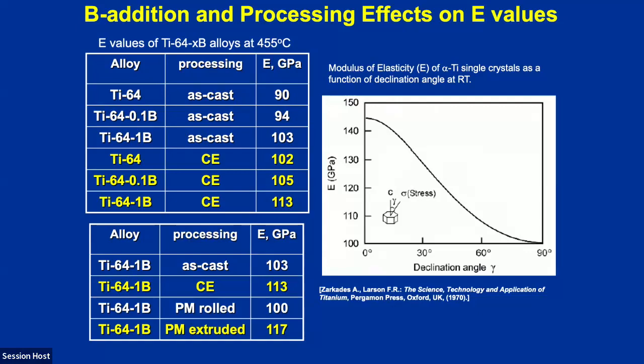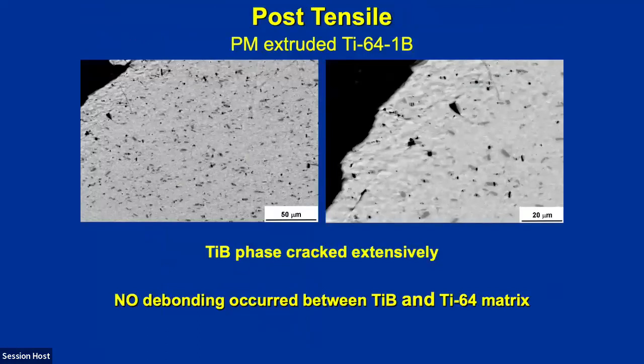If we look at the tensile tests, we've done a lot of experiments in situ to evaluate the damage progression in the materials, and we find, to no surprise, that this TiB is a reinforcing phase. It's very hard and very strong, and therefore it's taking on the load from the matrix. As it takes on the load from the matrix, it tends to develop the cracks first in the material, and we can see the cracking that happens throughout the titanium boride. Eventually, when the titanium boride cracks enough, then it'll shed load back to the matrix, and then it'll cause failure in the part.